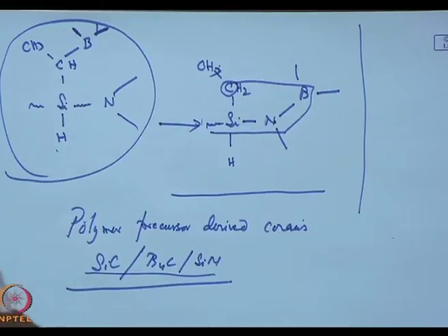So, in this particular one, while the thermodynamics, the pyrolysis rate, everything has to be very rigorously controlled, yet unlike the other systems I have talked of so far, I have got a mixed ceramic composite system which is mixed at the molecular level itself. I am not talking of particulate levels anymore.